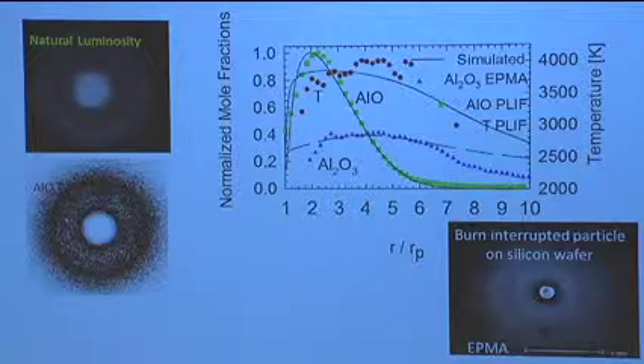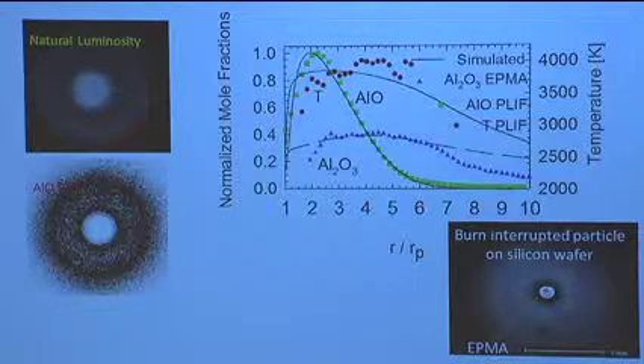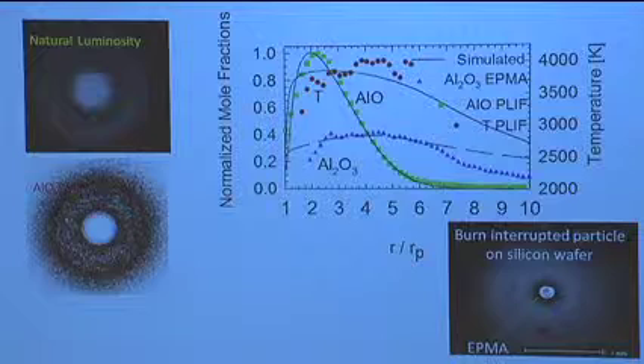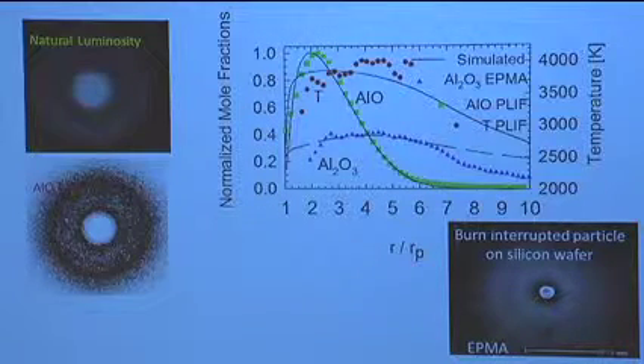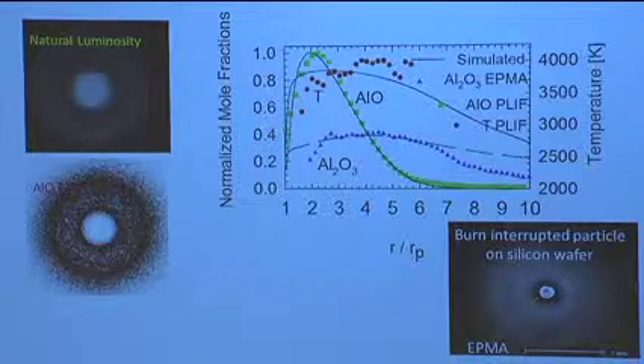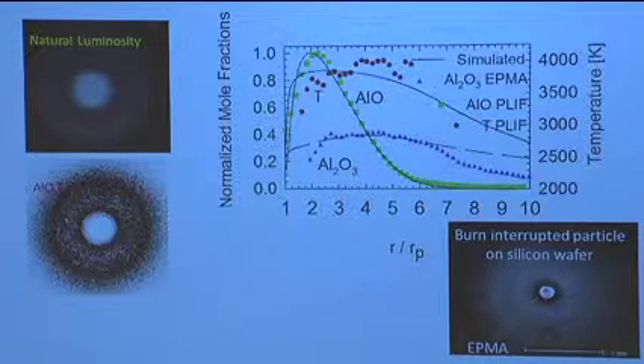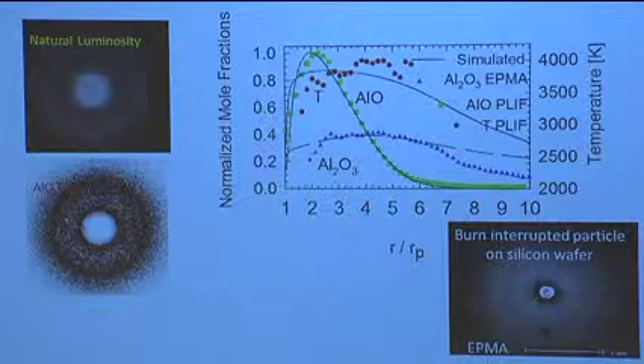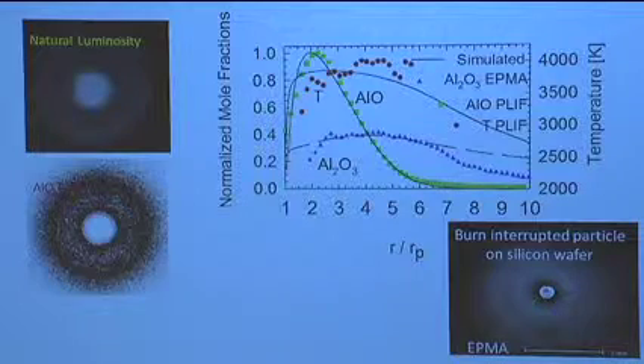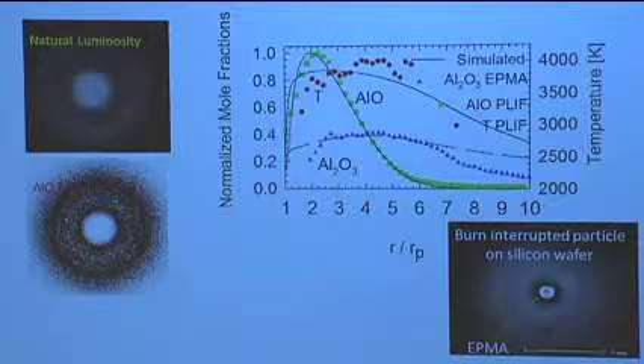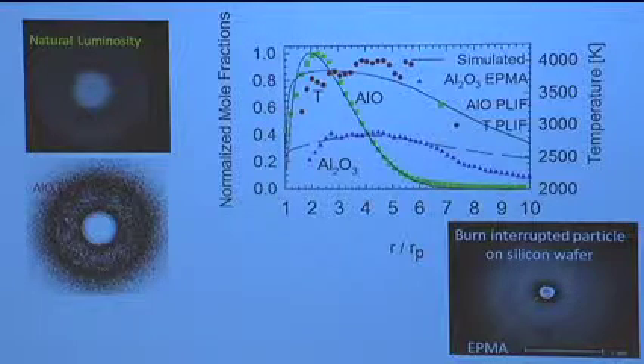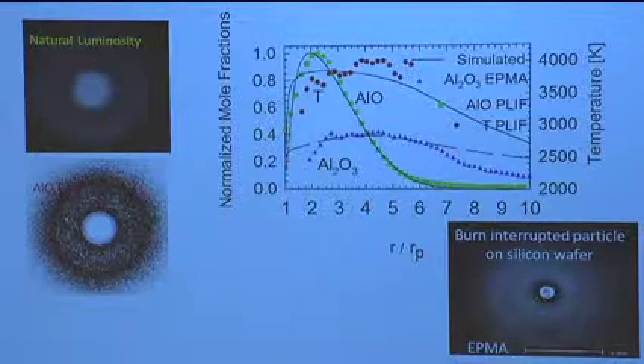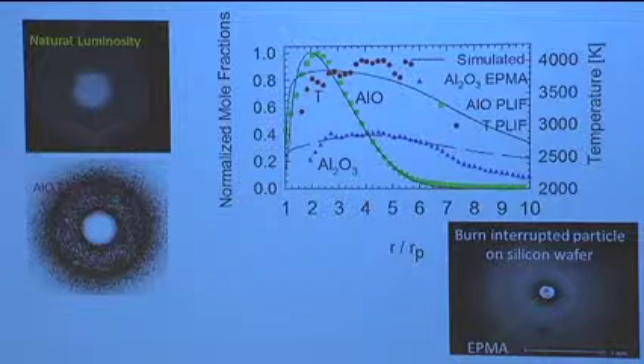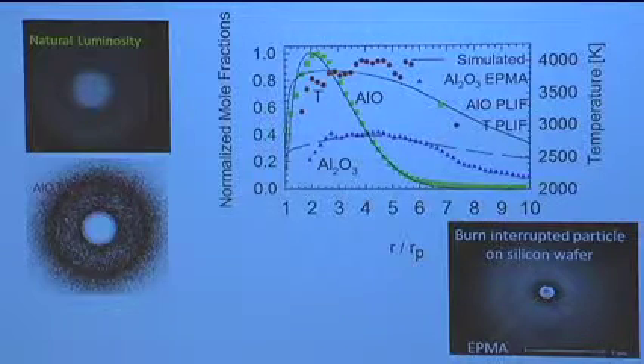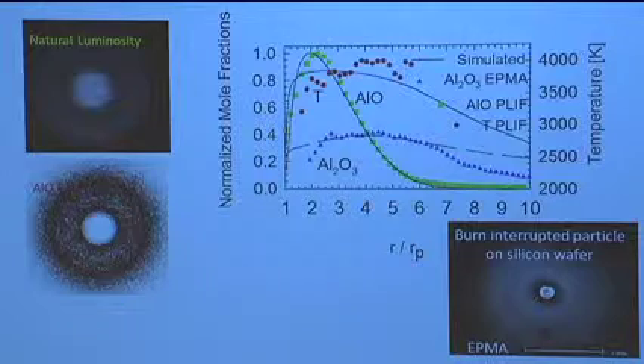Now to illustrate that experimentally, these are some experiments that I did with Fred Dreyer here at Princeton before I left. These are, again, looking at single particles of aluminum burning, and what we're looking at here is doing essentially some laser-induced fluorescent measurements, trying to measure the smallest suboxide around an aluminum particle as it burns. And what we do then is we actually fluoresce the aluminum oxide at 2 different wavelengths, and from that we can use a Boltzmann distribution to back out the flame temperature.